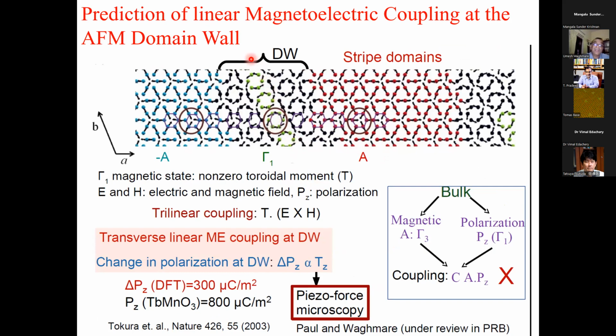It means the local crystalline symmetry here, in fact, the double group of this symmetry, is different from what is at the domain, bulk domain. Of course, that's not surprising because at the domain wall, naturally, you will often have lower symmetry. But in this case, the symmetry of the domain wall corresponds to the gamma 1 representation, which means you